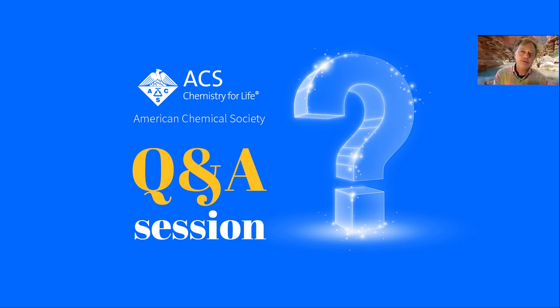That molecule has a huge free energy change for disproportionation. It's a disproportionation-like reaction. Two diiodides come together and they make triiodide and iodide. And an advantage of that disproportionation reaction is that triiodide and iodide are not easily reduced by the injected electrons in TiO2. And that's what allows those redox mediators to get away to the platinum electrode where they get regenerated.